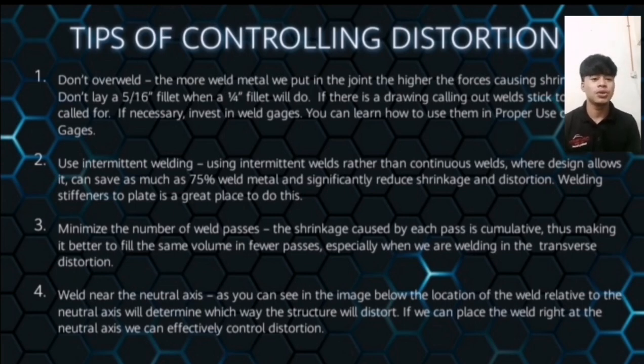Number two, use intermittent welding. Using intermittent welding rather than continuous welds, where design allows it, can save as much as 75% weld metal and significantly reduce shrinkage and distortion. Welding stiffeners to plate is a great place to do this. Okay, number three, minimize the number of weld passes.